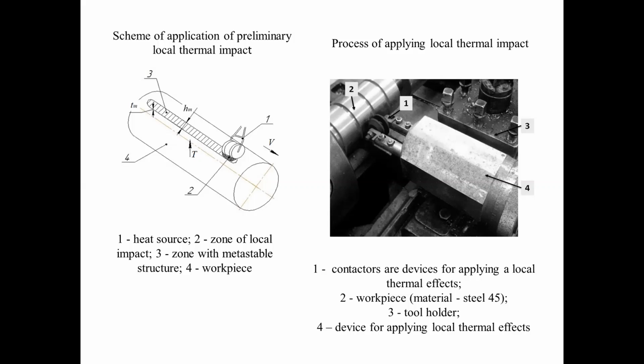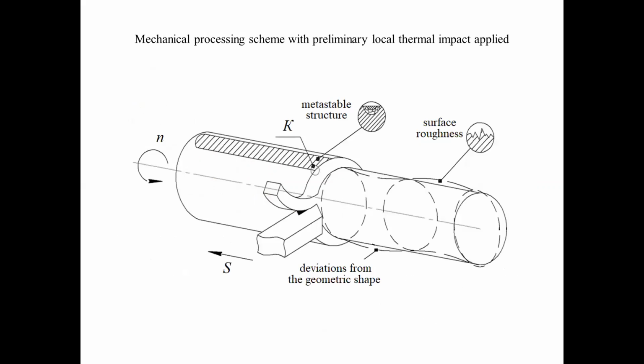Secondly, when machined, the resistance period of the cutting tool may be drastically reduced, since the top of the tool will be subject to periodic shocks. In order to prevent the negative factors described above in the future, it is necessary to know exactly how deep the chip is to be removed from the surface of the workpiece, and based on this, to set the local heat-affected depth of Tm, which on the one hand would not exceed the removed allowance and on the other hand would ensure a stable chip segmentation.